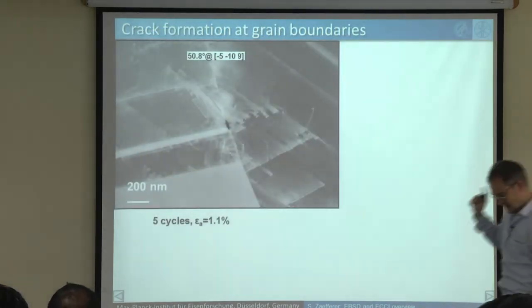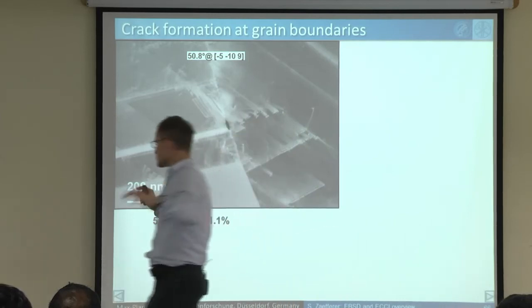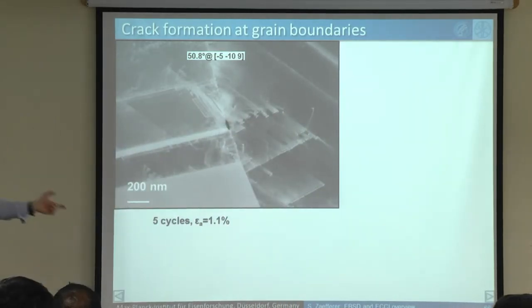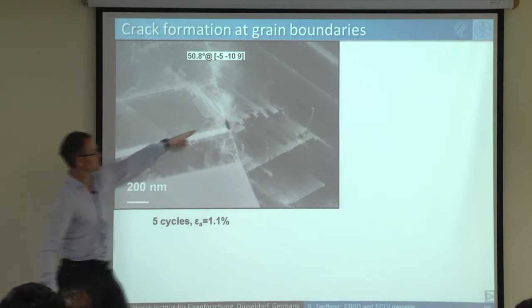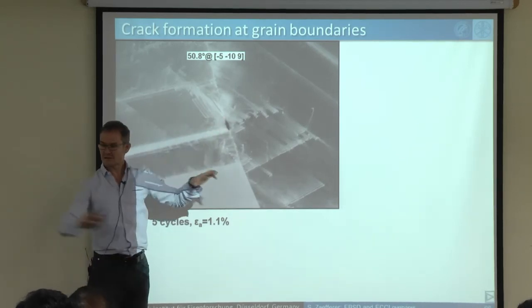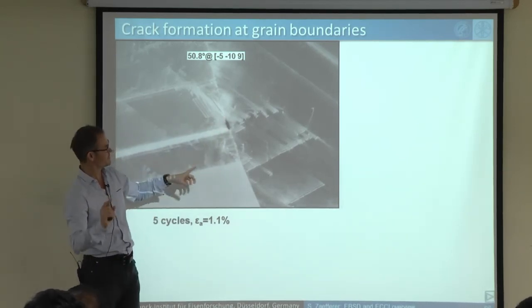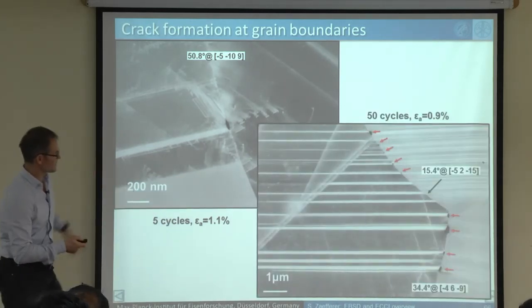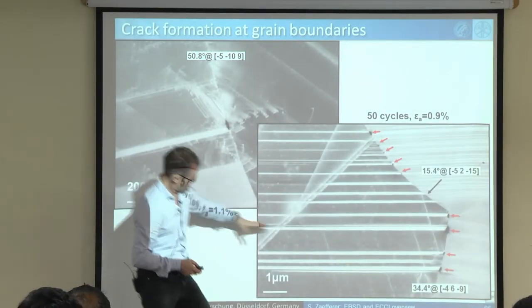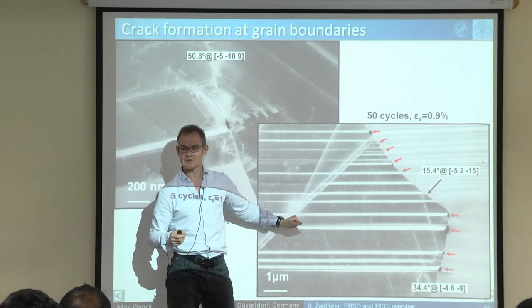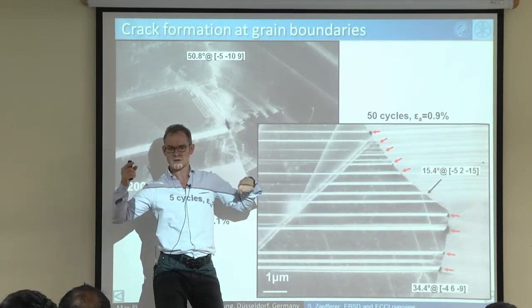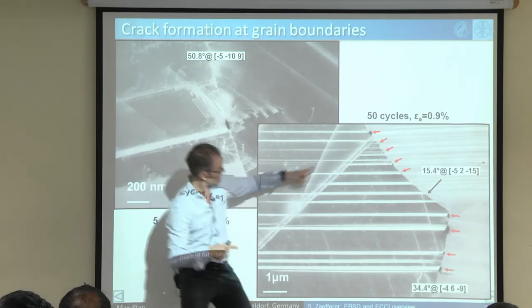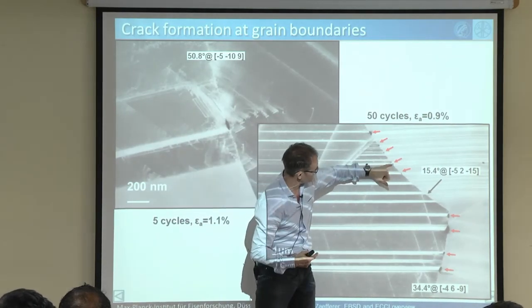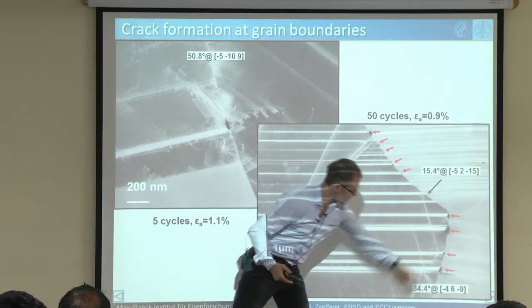And from that, then we continued fatiguing with hydrogen. When you do it without hydrogen, you can go 1,000 cycles and nothing happens. When you do fatigue with hydrogen, and you do only 5 fatigue cycles, you see the first cracks opening. Immediately, with hydrogen, the thing becomes so extremely brittle that immediately the material cracks, and you see it here actually, all these white lines is actually epsilon martensite, which forms much more severely when you have hydrogen in the material than if you don't have. And everywhere where this epsilon martensite ends up on the grain boundary, you get severe cracking.